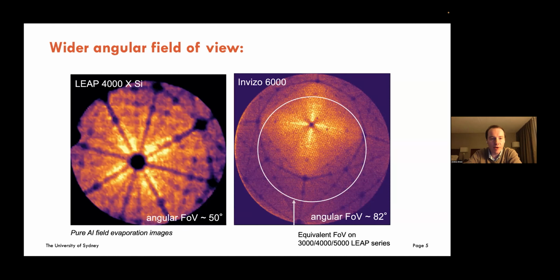So, of course, we've got the nice wider angular field of view, and maybe not such an elegant experiment as Levi performed on the same tip specimen, but if you compare a typical experiment run on the 4000 XSI in the voltage pulsing mode, you might get a detector map looking something like this, and you can overlay a stereographic projection of that crystal structure and calculate it's about a 50-degree angular field of view in this case.